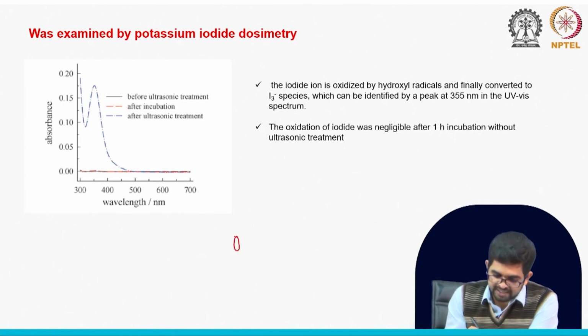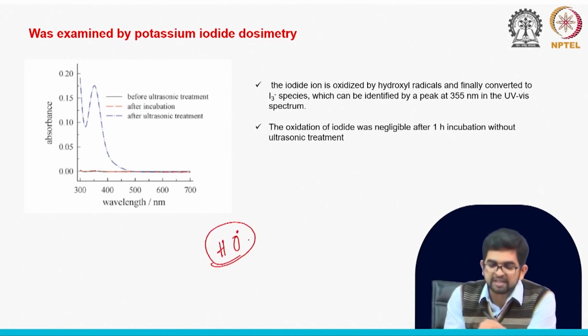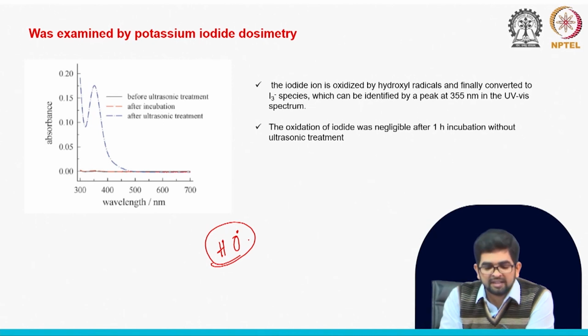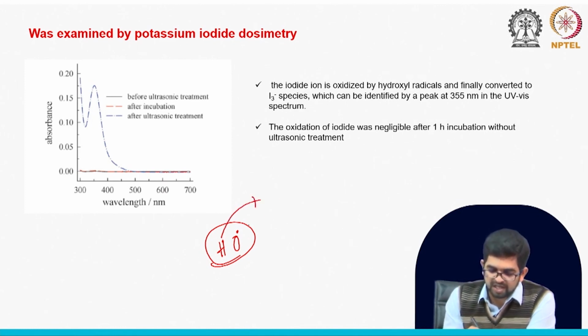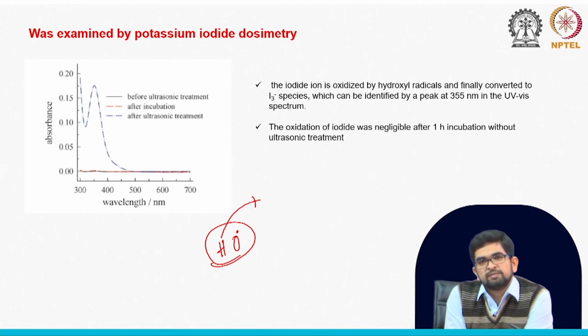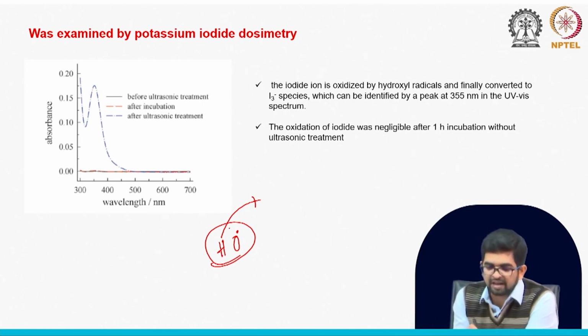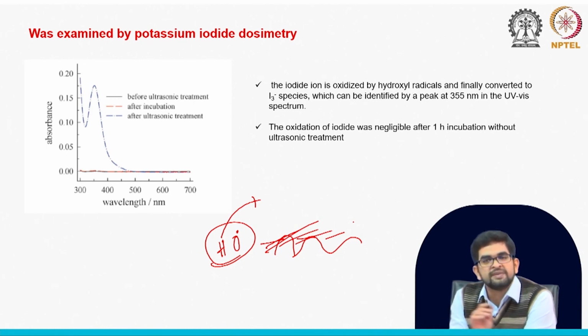In the Fenton reagent case, the OH dot hydroxyl radical is generated. It is well known that during sonication there is a possibility of hydroxyl radical generation. That hydroxyl radical, as I taught you, after mechanical polishing can attack this hill-and-valley type surface and dissolve the surface roughness, and you will get a smoother surface. The electrocatalytic activity can then be deactivated, right.